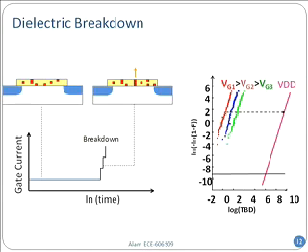Now this point where the bottom horizontal line is, that is 1 part in 10 to the power minus 12. That is this point. And that is because every company wants that if you sell 10,000 ICs, no more than 1 should come back. Now, every computer may have a billion transistors, 10,000, right? So this number would be on the order of 10 to the power 12 to 10 to the power 13.